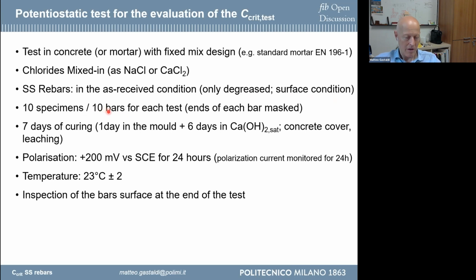You have to repeat the test for a number of specimens that is a minimum of 10 specimens, meaning 10 bars. It's also very important to mask the ends of the bar in order to avoid problems related to crevice corrosion. This is a problem related to the test generally. You only have to fix the time of curing. Generally, we consider a time of curing of seven days. This is also to reduce the problem related to leaching, which is also a problem related to a previous presentation. And then the polarization at 200 millivolts for 24 hours. We have to fix the temperature, for example 23 degrees Celsius. And at the end of the test, you can also evaluate the condition of the rebar with inspection.